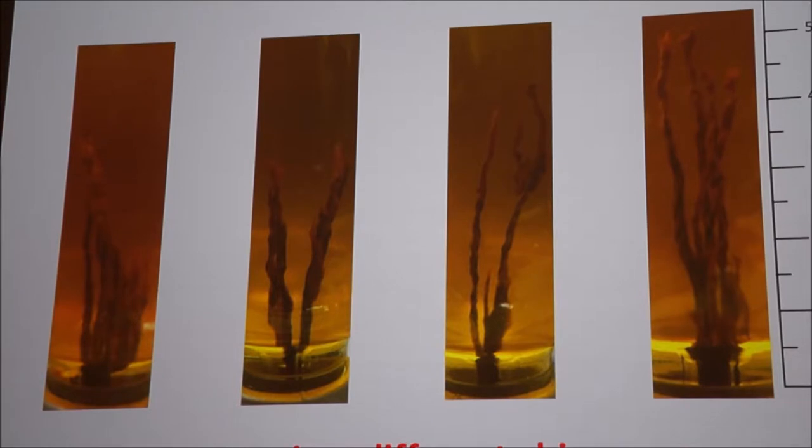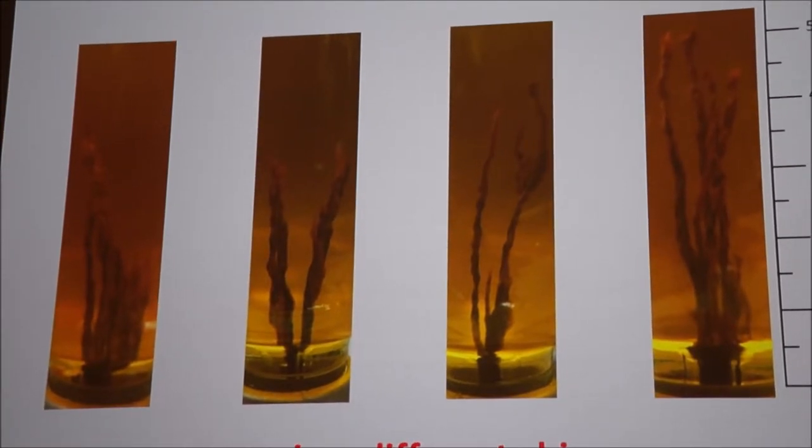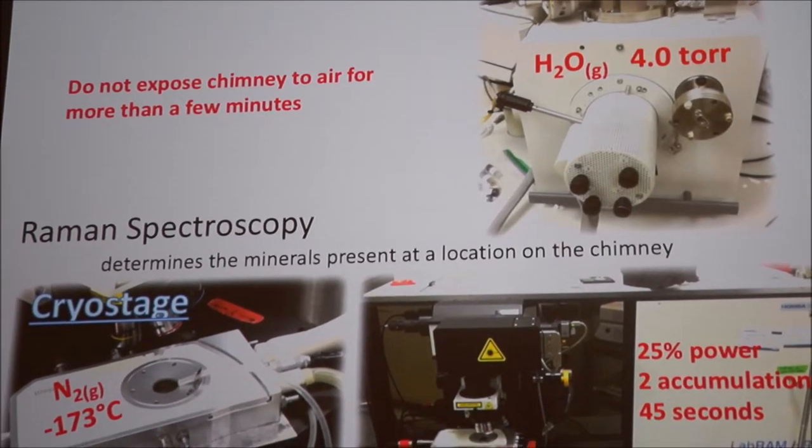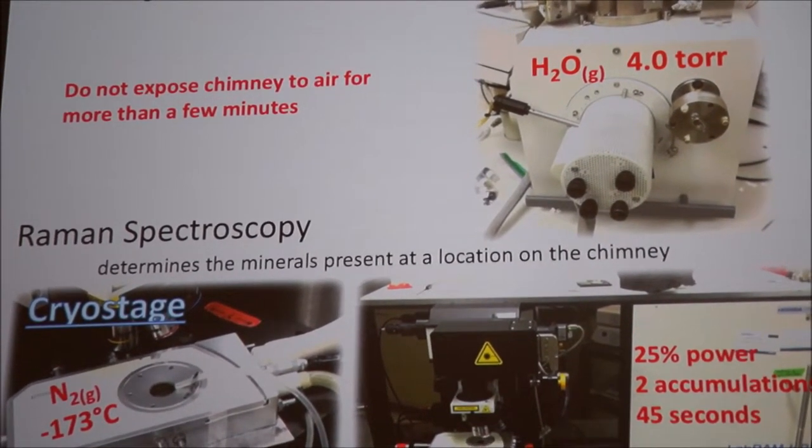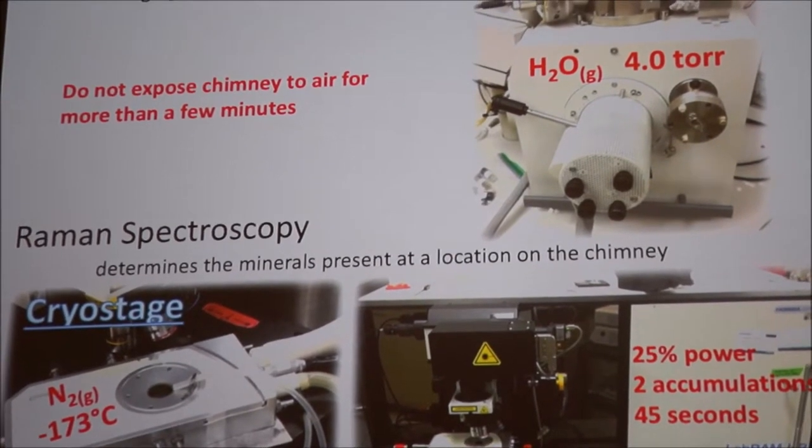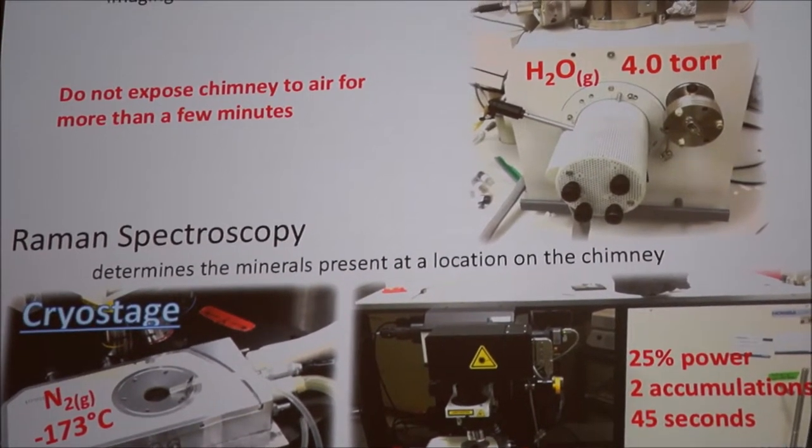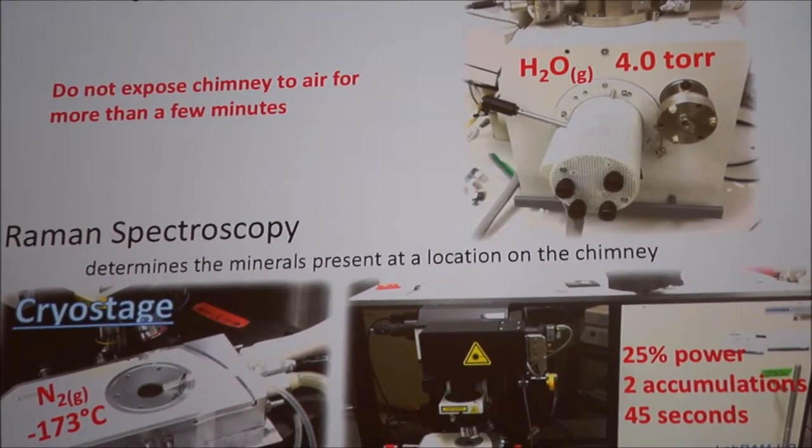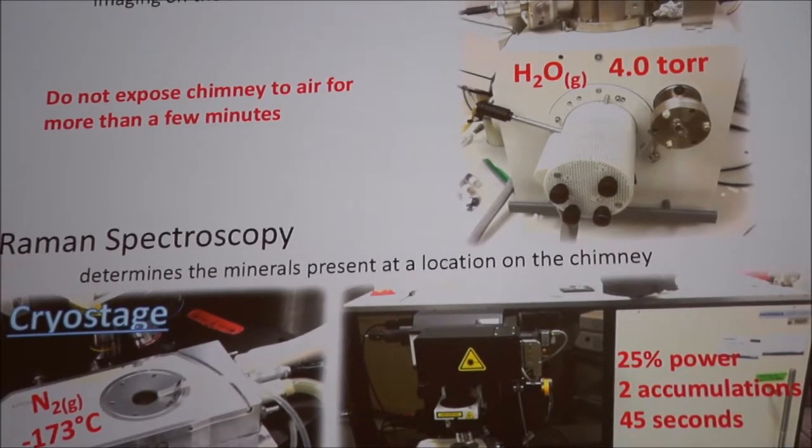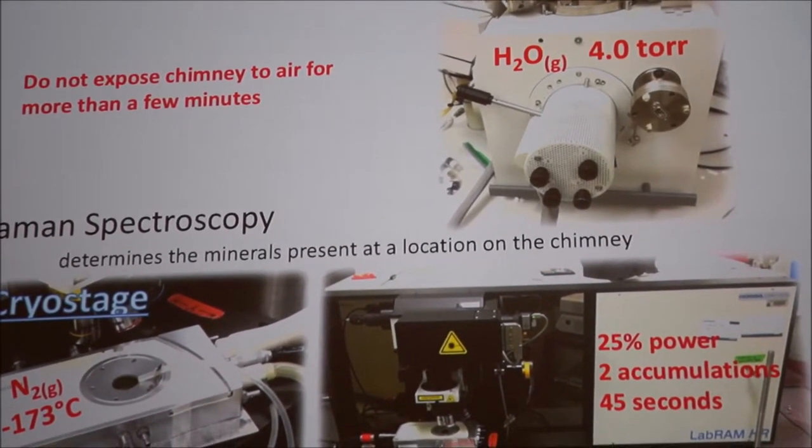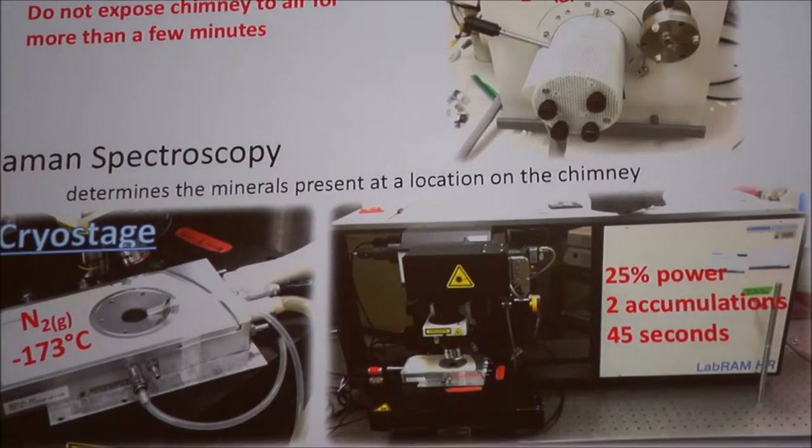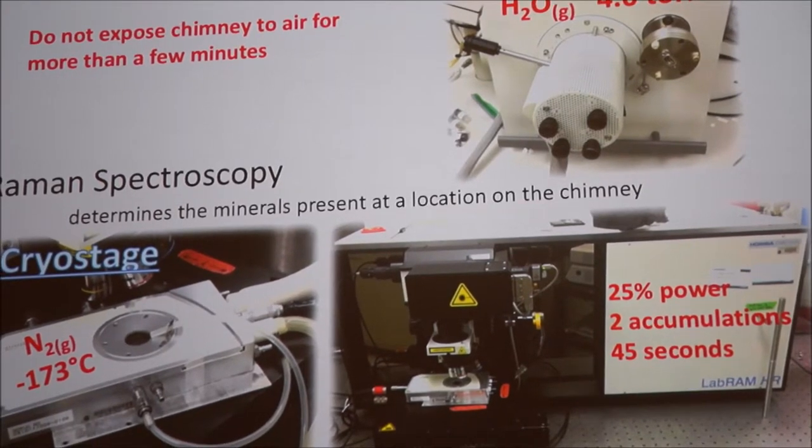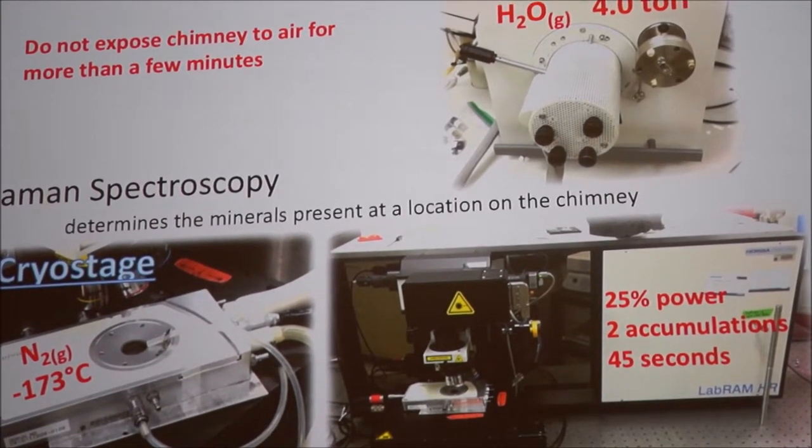Generally we always see something about three to five centimeters tall with green stalks with orange coatings and two to six-ish stalks each. The main ways that we analyze these are with environmental scanning electron microscopy and Raman spectroscopy. The simulants are sensitive to oxygen because iron can come into different redox states, so we have to be very careful to keep all of our experiments under an argon atmosphere and get them into the ESEM as fast as possible.